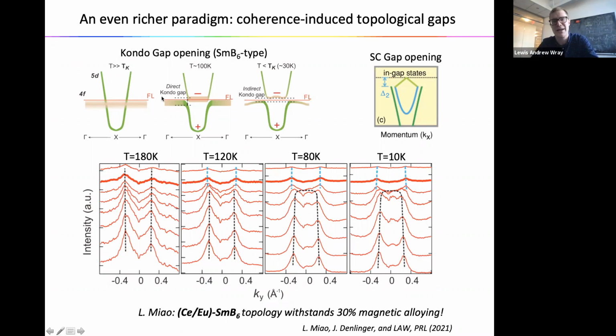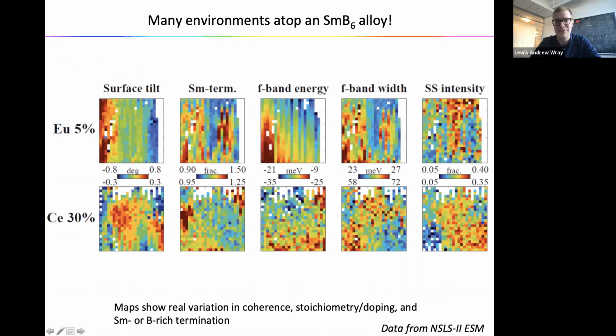It's strongly correlated, and you only have some incoherent F orbital derived states at the Fermi level associated with samarium that only gain coherence and start to look really like quasi-particles as you go to very low temperature. When they do, you have a topological gap that is going to be crossed by surface states. So we were in the middle of an investigation of these materials anyway, of what happens when you alloy them, when you adjust the chemistry, which there's a PRL that was just accepted that I won't delve into due to time constraints.